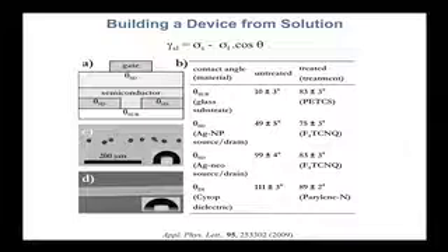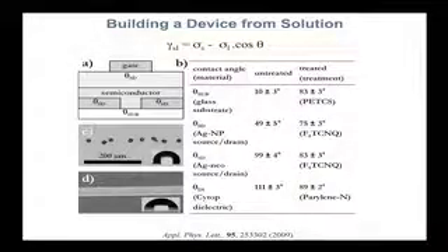So that's not going to be a very good device. So what you have to do is change the surface energy of both the substrate and the contacts, so that when the semiconductor is deposited, apart from not dissolving the materials that are already there, you will not see a difference in surface energy. So working on materials that can both modify the surface energy of the substrate, modify the surface of the electrodes, and add some electronic properties so that injection or transport becomes better, the interface between the metal and the organic semiconductor is very important.